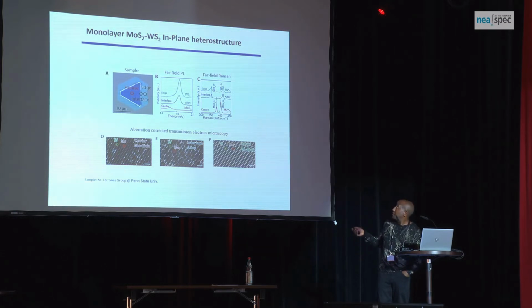So this is the peak for WS2, a known PL peak, and MoS2 somewhere here. And at the interface, you have somewhat in between peak. And the Raman modes as well are quite separated. So it's nice from a hyperspectral imaging point of view when you try to look at both of these materials in one go. So what's important is if you look with TEM